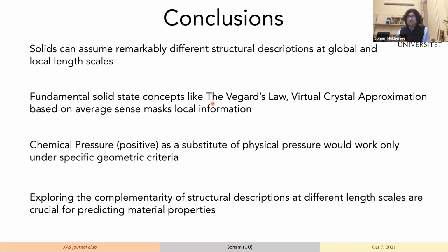Chemical pressure, only the positive part, of course, because that is the only equivalence that you can draw to hydrostatic pressure. But this can be substituted only on specific geometric criteria, which means that the site substitution would involve an angle invariance process. The moment angles change, typically the system would probably go into experiencing change of angles rather than distances. And finally, with one example of barium titanate co-doped with manganese and niobium, I have shown that the complementarity of structural descriptions is extremely important to see such local distortions and how they influence material properties. With this, I'd like to conclude.